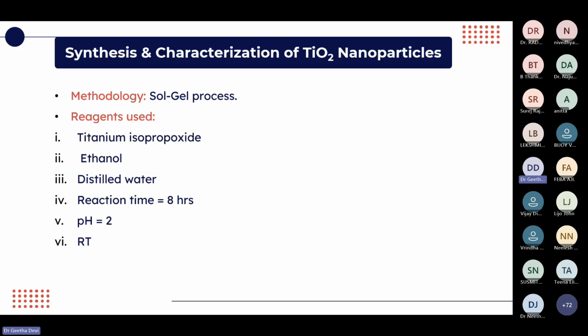The next type of nanoparticles we have synthesized is titanium dioxide, and it is synthesized by the sol-gel method using titanium isopropoxide, ethanol and distilled water. Reaction time was kept at 8 hours with a pH of 2. The reaction was carried out at room temperature.